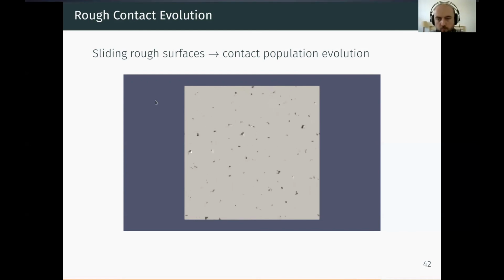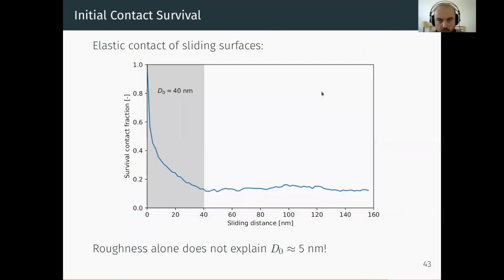So what I did was to take the AFM roughness measurements from the experiments that were given to me by Juliette and do elastic contact simulations of two sliding surfaces. And what I measure is the survival contact fraction. So the amount of contact area, the fraction of contact area at a given sliding distance that is common with the initial contact area. And this survival contact fraction decays as a function of sliding distance until it reaches a steady state, where basically all of the memory of the initial contact area is lost. And this decay occurs in my simulations over a distance of 40 nanometers.